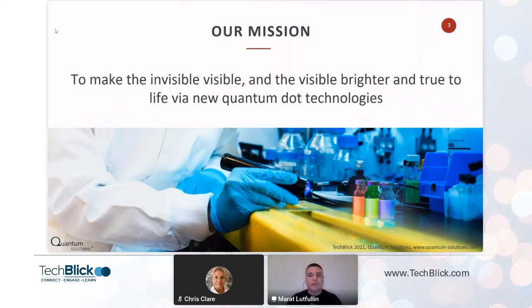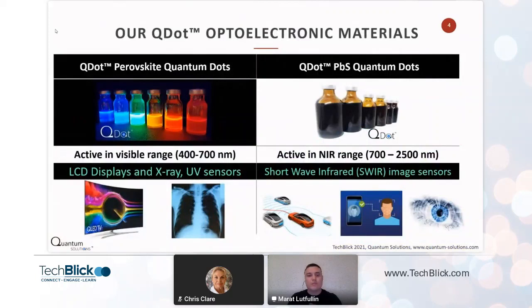The mission of our company is to make the invisible visible and the visible brighter and true to life via new quantum dot technologies. And these quantum dot technologies include two product lines. On the left is our QDot Perovskite Quantum Dots. They emit light in the visible range from 400 to 700 nanometers, and we developed them for two applications, first for LCD displays, and second for X-ray and UV sensors. Our second product on the right is QDot PbS Quantum Dots. They're active in the infrared range from 700 to 2500 nanometers, and we developed them for shortwave infrared image sensors. We collaborate with many sensor and display companies worldwide to help develop new devices with our materials.